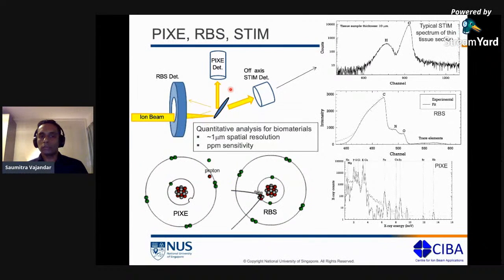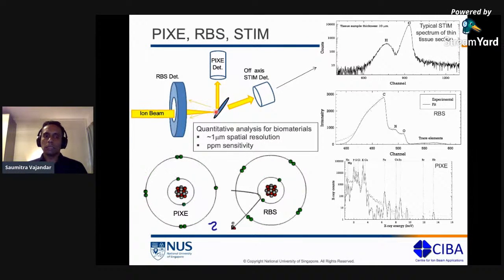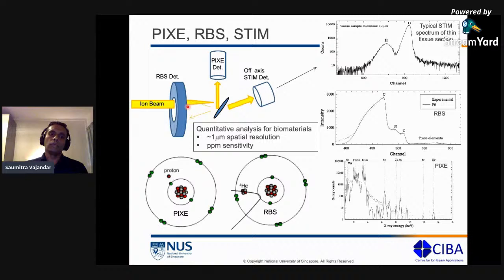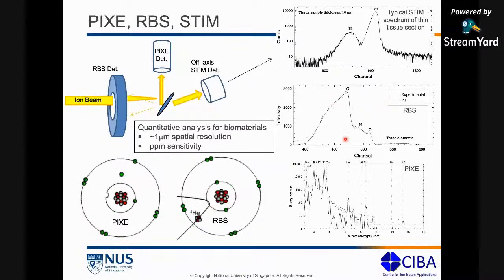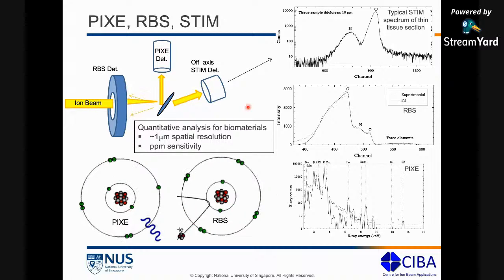When we do that, we are going to have three things happen at the same time. We are going to have a backscattered signal. So some of the ions will get backscattered. The RBS detector will detect these signals. So we have an RBS signal coming out, giving rise to this RBS spectrum. Then we have the PIXE detector, which detects the X-rays coming out from the sample. So this gives you the PIXE signal, the X-ray signal.